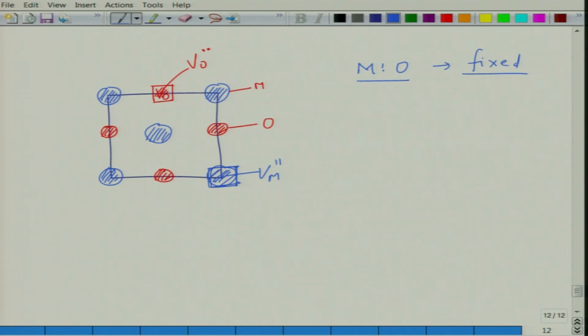And generally these metals and oxygen diffuse out of the system until you reach equilibrium. So this is the equilibrium defect. You will have some of these defects always present thermodynamically in the system. We'll do the thermodynamics later on. And these defects are generally preferred when anion and cation are of equal or comparable sizes. So this is for MO.